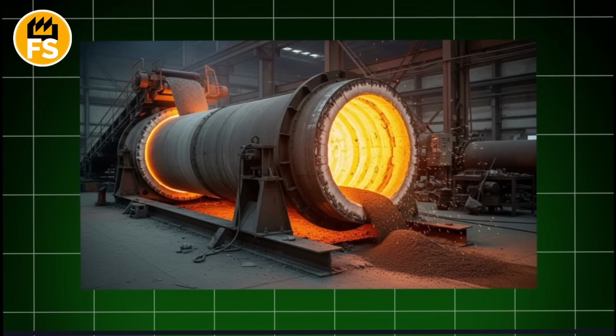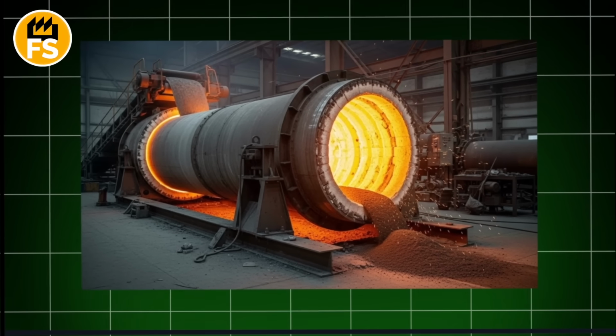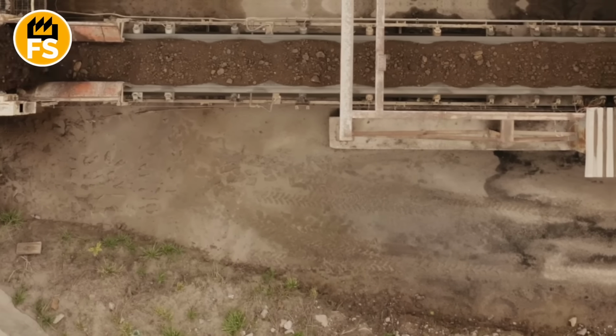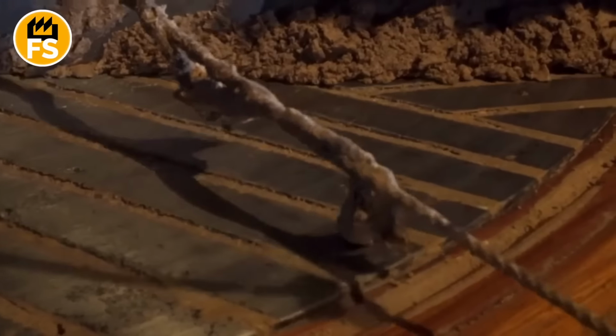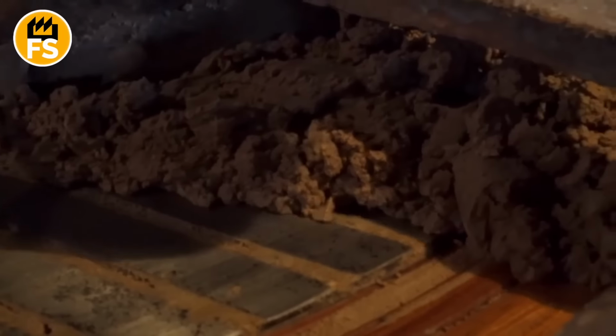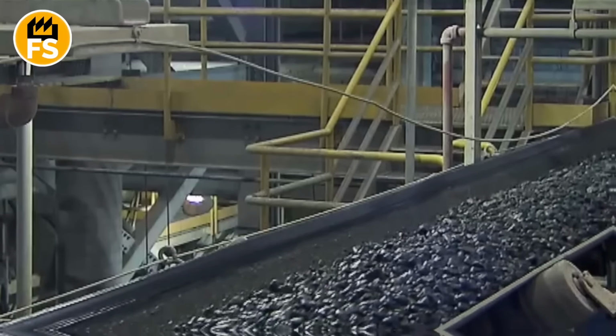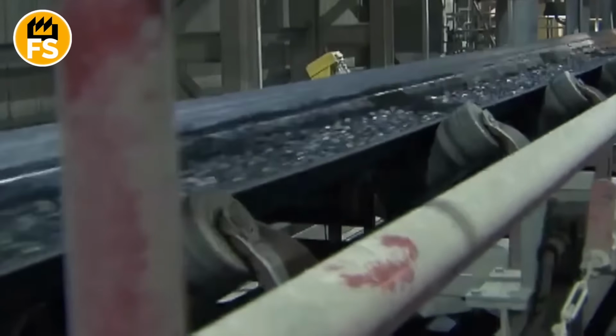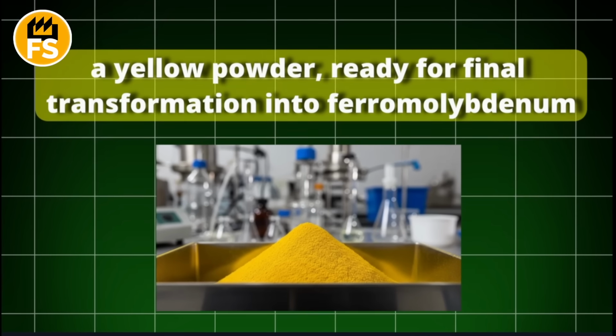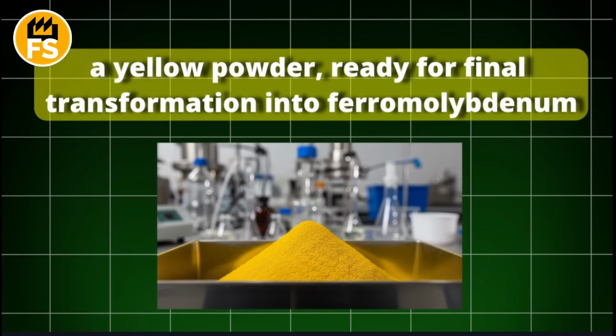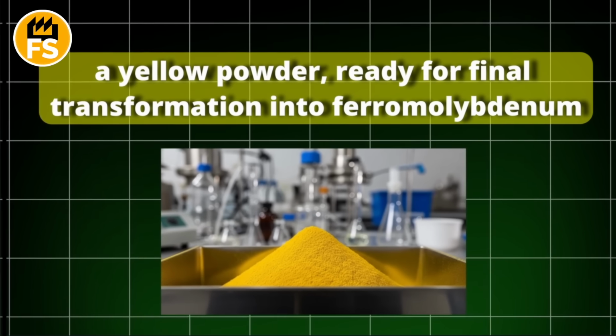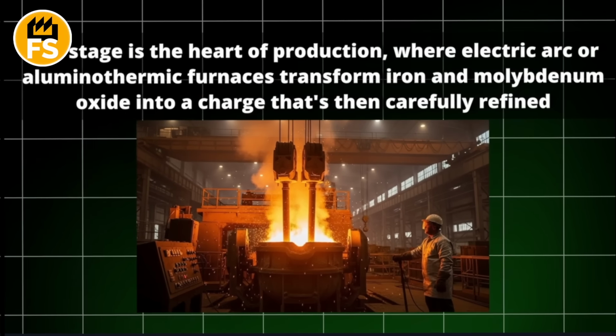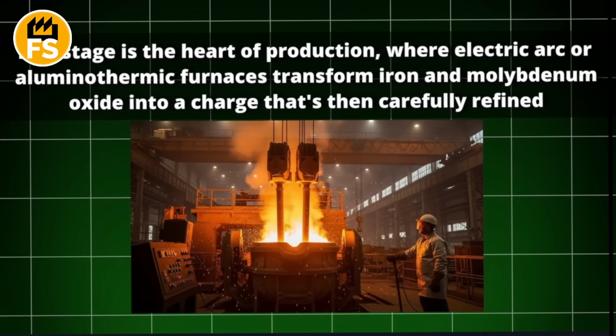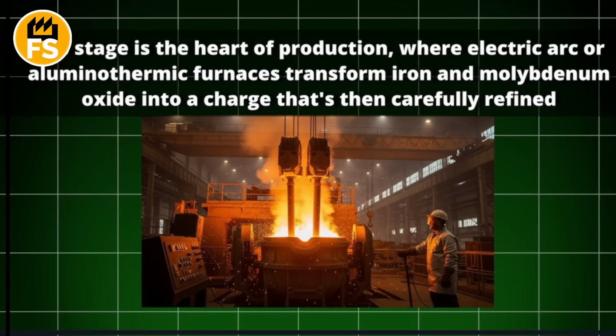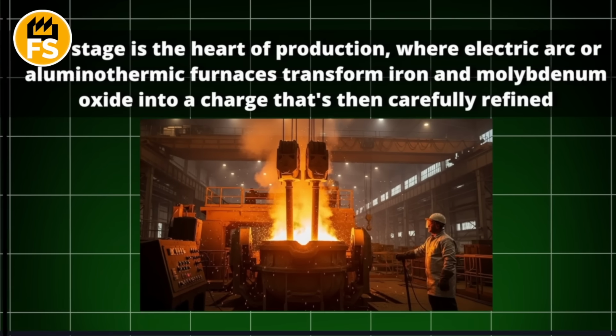The resulting concentrate, a moist gray powder, is dried in rotary kilns at temperatures near 600 degrees Celsius, transforming it into a finished product for smelting. This stage takes hours, but determines the quality of the entire chain. After roasting, the molybdenum concentrate transforms into pure molybdenum trioxide, a yellow powder ready for final transformation into ferromolybdenum. This stage is the heart of production, where electric arc or aluminothermic furnaces transform iron and molybdenum oxide into a charge that's then carefully refined.